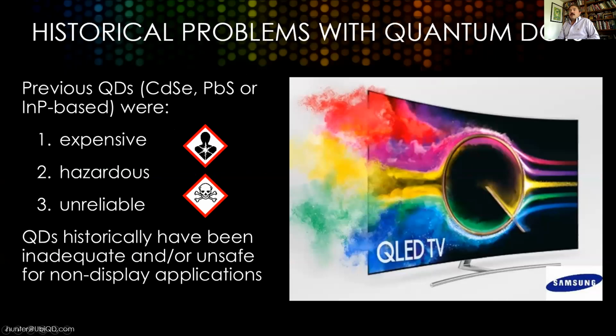And I think many of you are quite familiar with quantum dots. Historically, there are some challenges there, in particular with toxicity. The old school quantum dot was cadmium selenide, or if you wanted to go into the infrared, you would use lead sulfide. More recently, indium phosphide has become popular, for example, in a host of different TV products on the market today. In all of these cases, the quantum dots are hazardous, in some cases highly cost intensive, and have reliability issues, which ties into the cost, because if you have something that's not air stable, you have to spend more on encapsulation. And so again, this has made them historically inadequate or unsafe to use in non-display applications.